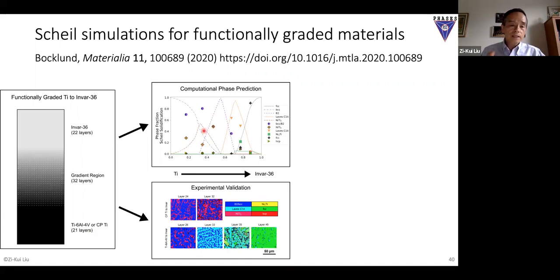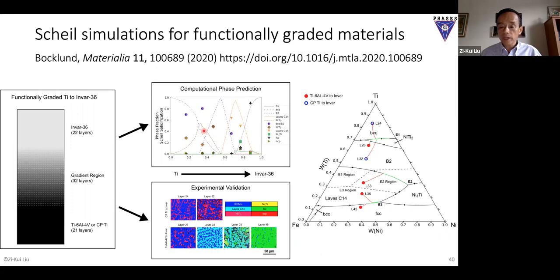Now in reality this is more than 3 components, but you can use 3 components for illustration. So that's the liquid projection - you see the iron, nickel, titanium liquid projection. It turned out it depends on going from titanium to the iron-nickel alloy.